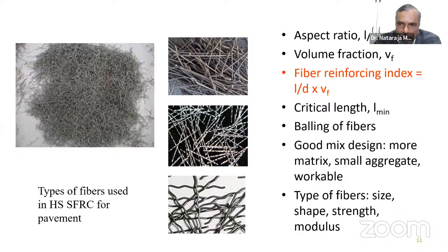Aspect ratio of the fiber comes into the picture, that is L by D. What is the length of the fiber? Equivalent length divided by the equivalent diameter. And as the aspect ratio increases, of course, the mechanical properties of the concrete might increase. But other related properties, especially from the rheological point of view, the workability and other things, might decrease to some extent. And how much fiber you're adding is another question you need to ask. That is where the volume fraction of the fiber comes into the picture. As the volume fraction of the fiber increases, many of the mechanical performances of the concrete increase. But as I mentioned, the workability of the concrete decreases to some extent.